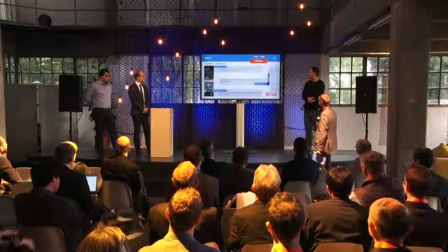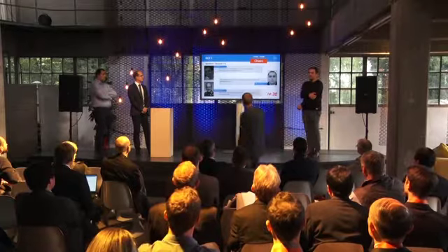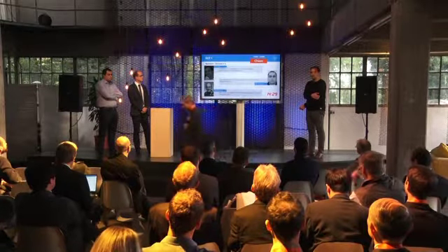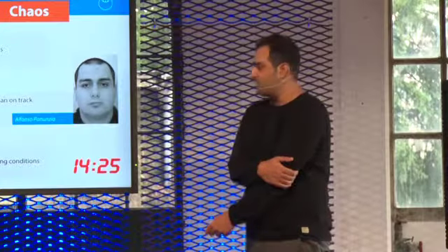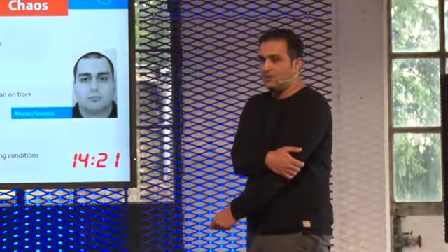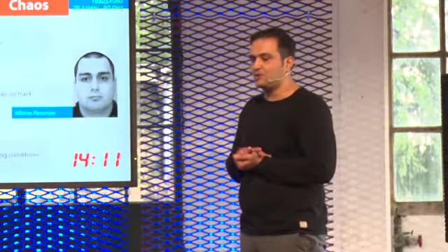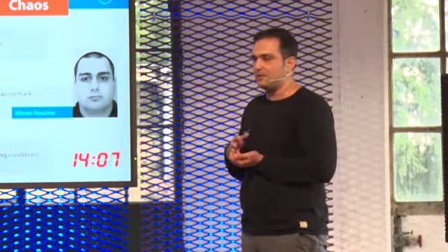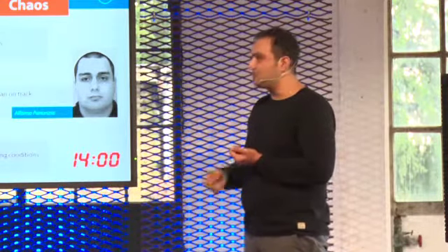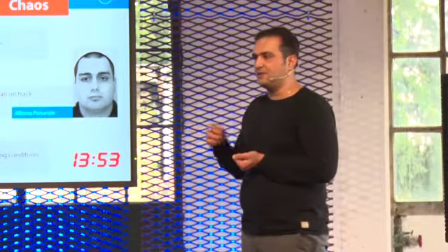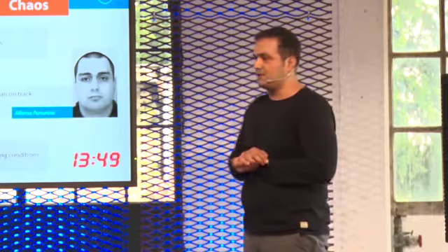Yes, modeling of cyclic plasticity and phase transformation during repeated local heating events. So for us, it was important to get some knowledge about the material behavior when it is subjected to these local, frictional heating events. So we wanted to improve our modeling in terms of kinetics of the phase transformation, the description of the thermal strains, and also, more importantly for me, to describe a proper constitutive model. In this case, it is a plasticity model with Chaboche mixed isotropic kinematic hardening, to be able to predict the material behavior when it is subjected to thermal loading and also rolling cycle loadings in our later studies.